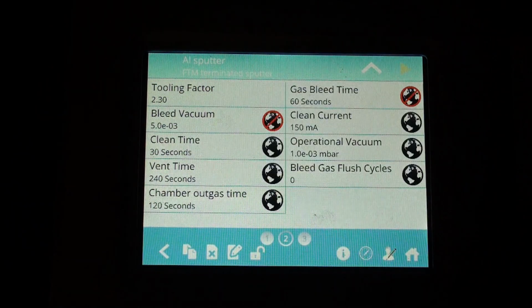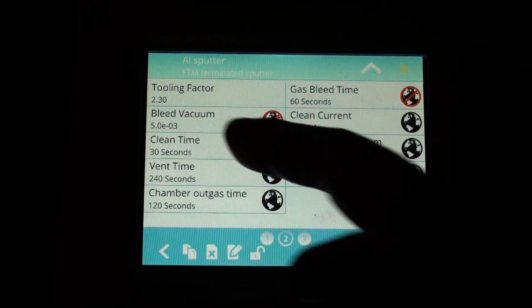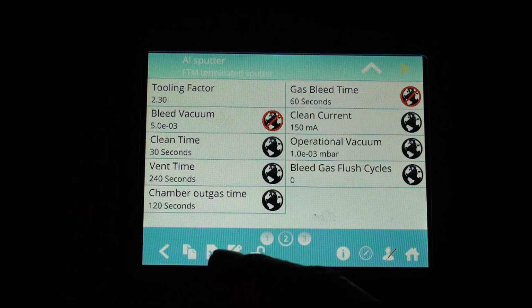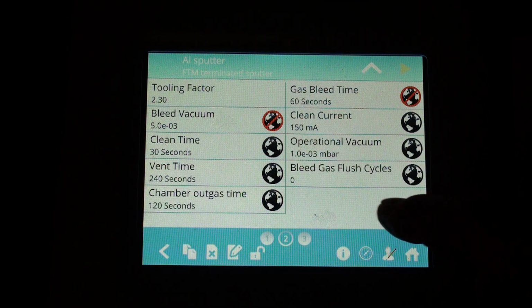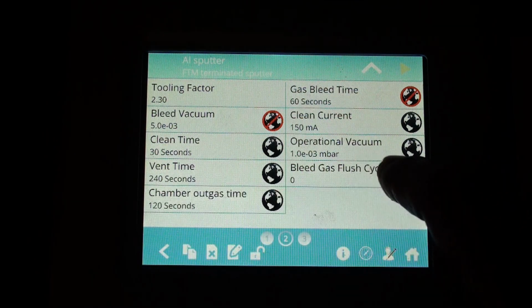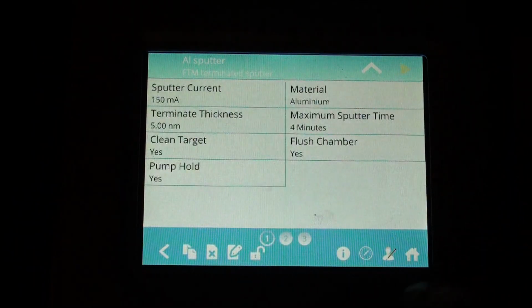By the way, if you see a circle with a line through it, it means that that is no longer a default process. When they're just dark like this, it means that it's a default factory process. You can increase the clean time if you wish. Vent time is as needed. Cleaning current, it goes to the max because it's a single head system. And that's just stage rotate. So that's how you would set it up on your single target system.